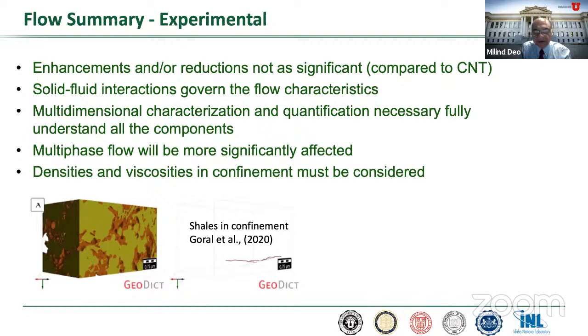So the main summary, or again the takeaway from what we have seen so far for flow in confinement, which is what we have been trying to answer: do we see these significant enhancements? And if so, what is the order of these enhancements? Our investigations at least show that they are not significant in the systems that we have seen compared to CNTs. And then depending on the type of fluid and the wettability of the system, we actually see more of a flow reduction. And this will have more of an impact in multiphase flow when we start looking at the multiphase flow components of it.